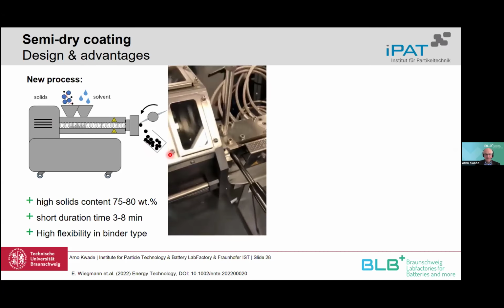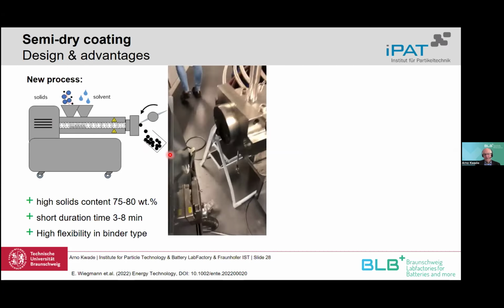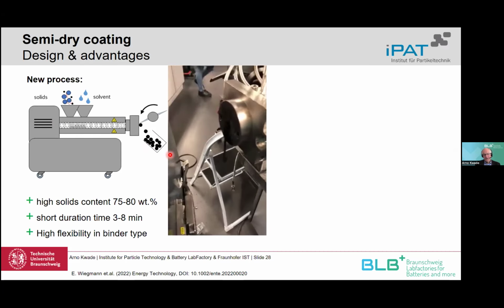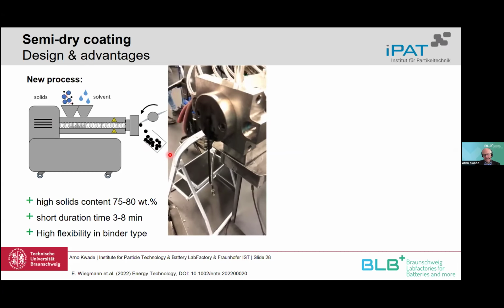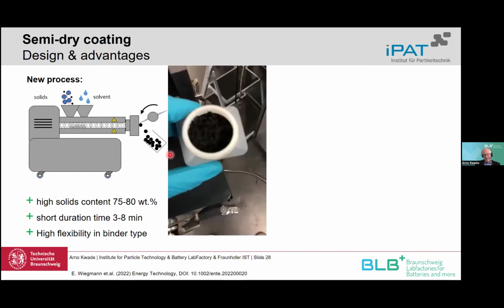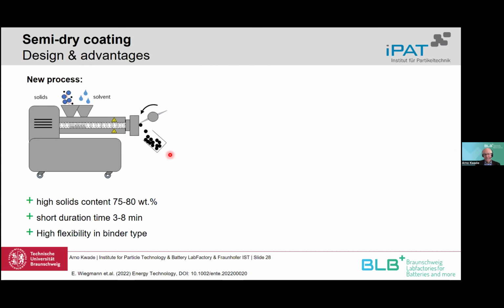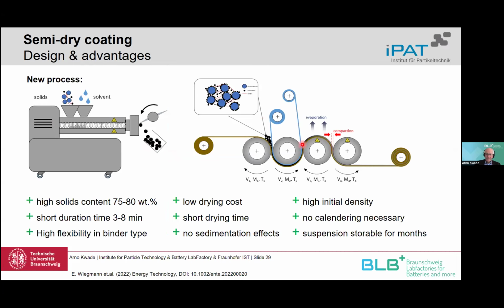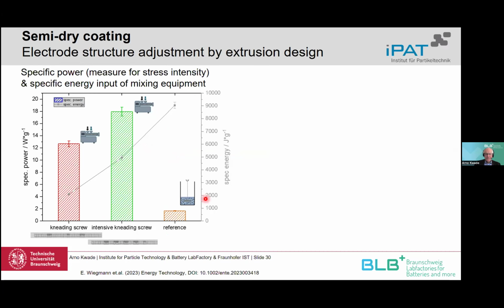Here is a small video where you can see the cutting of our extrusion strands. This gives us nice granules, which are shown here, which we then dose onto a calendering machine. On the calendering machine, we can then form a nice thin film with really good properties. And you can see here different ways to process our active materials and conductive additives: with a normal kneading screw, with an intensive kneading screw, where we have more kneading elements in the screw, or with a normal planetary or dissolver process.